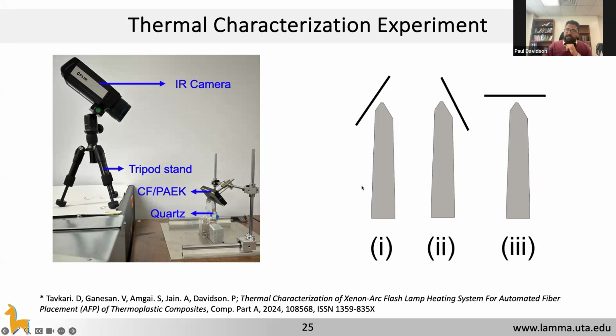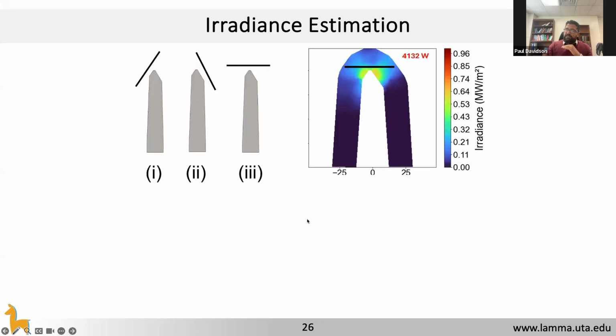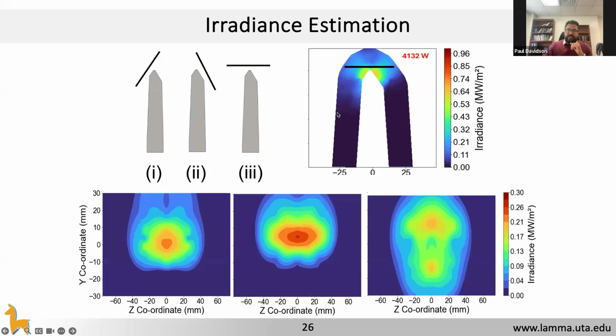We did it for 3 locations, which are facet 2, facet 4, and facet 3. By facet 2, I mean that you keep the plate parallel to facet 2, then parallel to facet 4, and then parallel to facet 3, which is right on the top. So if you look at the incident radiation profile, which we can estimate now because we have an envelope, we can put the plate at different locations and then interrogate what the flux profile on the plate itself would be.